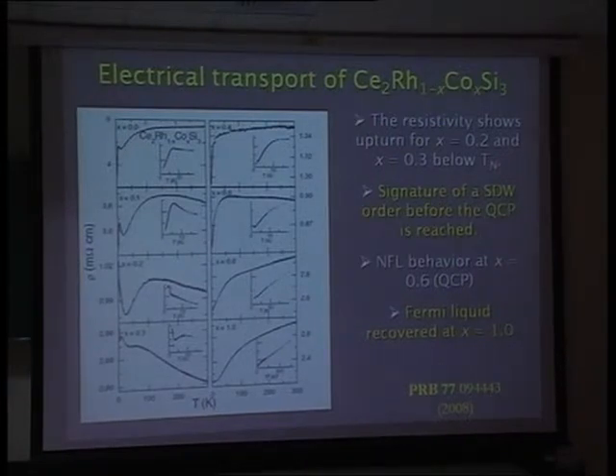And at the other extreme end, which is Ce2CoSi3, it is a perfectly Fermi liquid system where the resistivity goes as T squared, and the Kondo coupling is complete here. And at x equal to 0.6, we see the resistivity goes linear in T. So this is the non-Fermi liquid kind of behavior that we expect at a quantum critical point. This is the composition that corresponds to it.